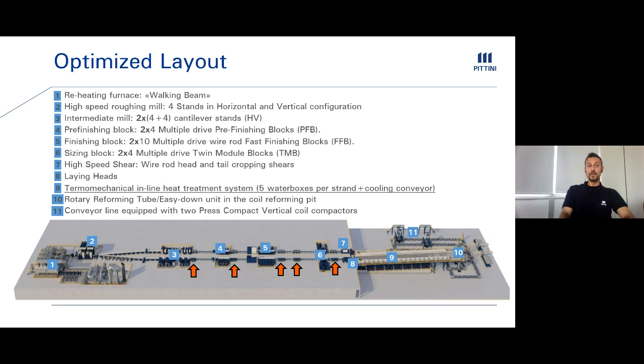After that, we have the 4-stand high-speed roughing mill that was specifically designed in order to have the optimal deformation speed and reduction of area needed to squeeze the material and seal all the micro voids and micro defects present inside the original billet. Of course, just to digress for a moment, we need to remember that the billet is a cast product. So this means that inside the billet there are all the metallurgical features of a cast product, and we need to take care of this since the beginning of the rolling process.